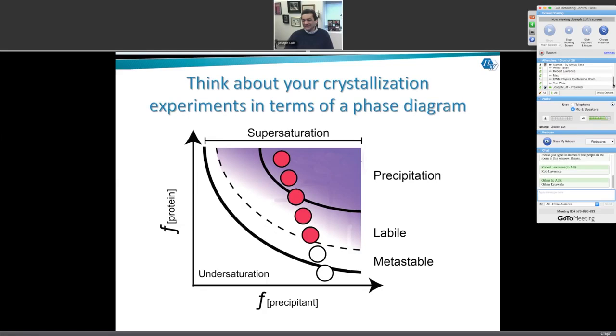You're cutting out, but I think your question was, why do you get a UV signal from microcrystalline precipitate and not from amorphous precipitate? The microcrystalline precipitate is more concentrated. The protein is more concentrated, so it's actually able to give off a signal. Whereas in the amorphous precipitate, the actual concentration of the protein is lower. It's more distributed, so you can't detect it over the background signal that you might get from just the solution itself. Okay, thanks.